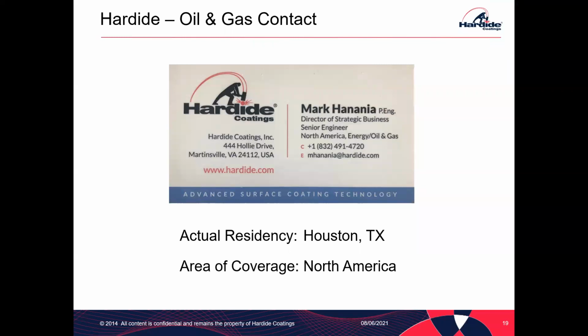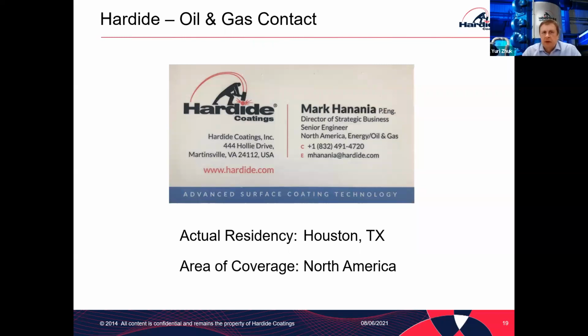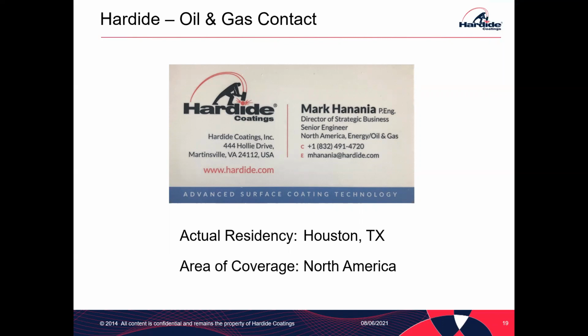Okay, good. Hank Vandenberg has a follow-up. Is it used on tools for machining aluminum? We have never really tried that application, but the coating that we produce is chemically tungsten carbide. And tungsten carbide is very good for machining aluminum because it does not form intermetallic compounds, unlike iron-based tools. So that's something we can try. Okay.